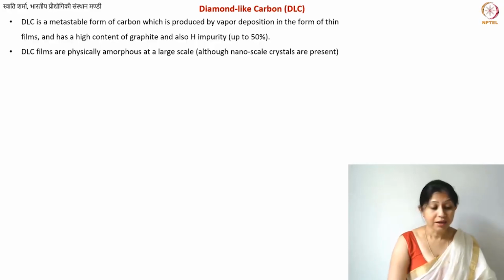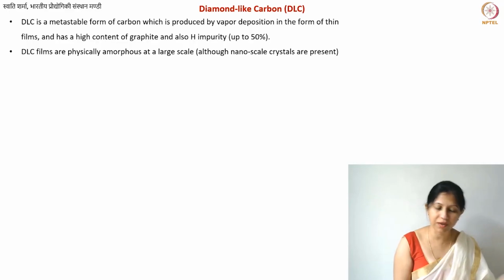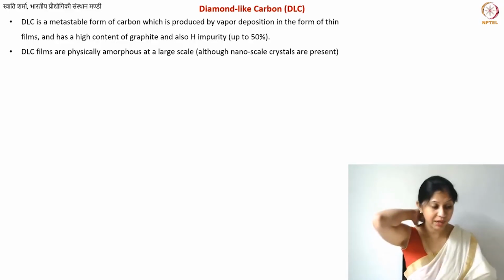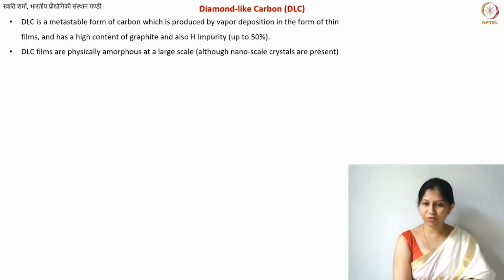Okay, but again, diamond-like carbon is not just one type of material. Depending upon the fraction of sp2 and sp3 carbon and hydrogen, you can further divide this material into different classes or subclasses, subcategories. Importantly, diamond-like carbon is pretty much always called an amorphous form of carbon, because again, it depends on the scale at which we are talking. We talked about other types of carbon materials, non-graphitizing carbon, for example glass-like carbon. Physically, yes, it shatters on breaking, and that is why you call it an amorphous material, but it is electrically conductive. So whether you should call it amorphous or not is a question.